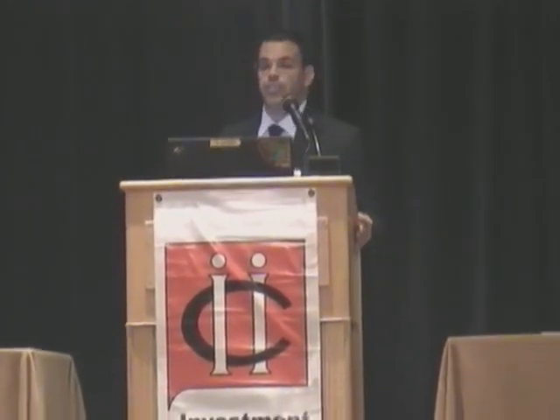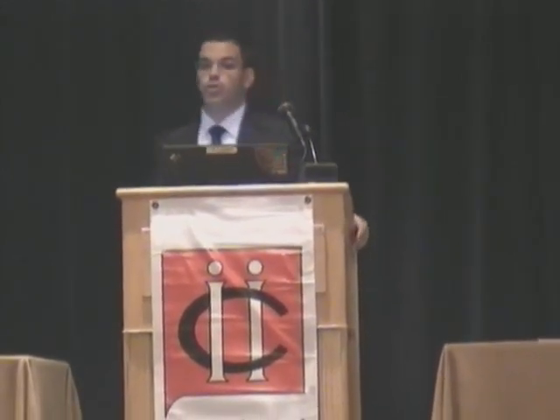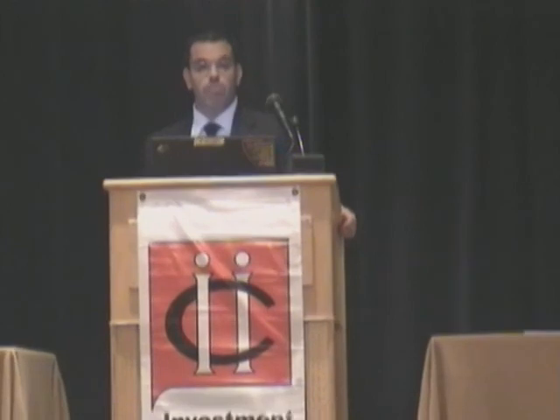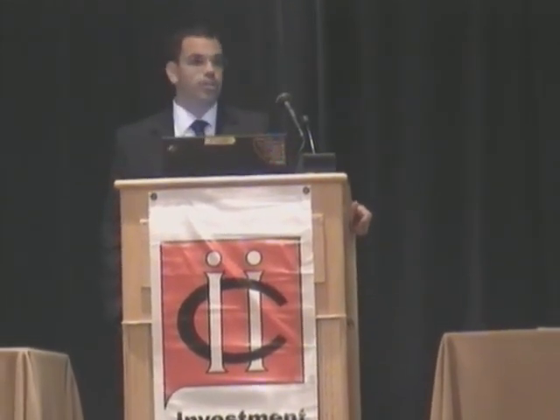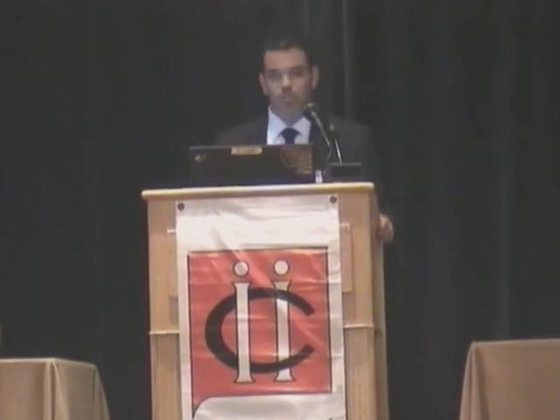So, results. The new degassing process and control allowed us to determine that the defects observed in the NDT were definitely micro-shrinkage indications and not gas porosity as we're used to. The phosphorus use enabled us to be sure that the same solidification behavior is occurring every single day. Meaning that if we have a micro-shrinkage phenomenon, it's not because of playing with temperature and it's not because of gas. It could be assembly.